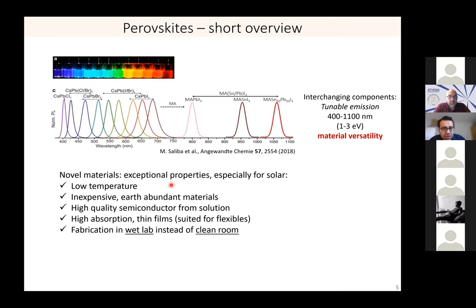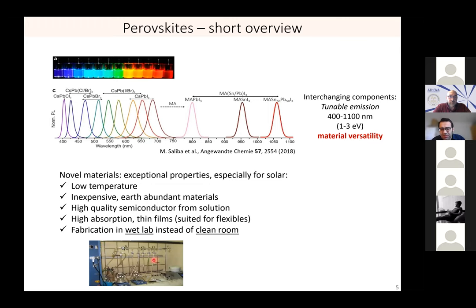They became very interesting. You see it here, these colloids, because they can be tuned from 400 to 1050 nanometers by exchanging the different components. So starting from cesium lead trichloride, the violet, and then towards the infrared, resembling more the bandgap of silicon, tin and lead mixtures together with iodide are pushing the bandgap there. And this is interesting because it's low temperature processable, inexpensive, earth abundant materials, a high quality semiconductor from a solution. And because it's a direct bandgap material, it has a high absorption. Therefore, it only requires a very thin layer, even on a flexible substrate, to absorb a lot of light, and the fabrication can be done in a wet chemistry lab instead of a clean room.